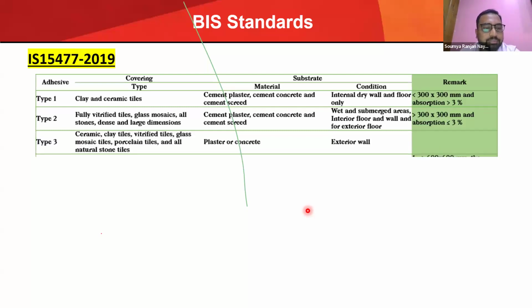Type 3 is the same kind of area we can use, but it allows for both external walls and internal walls, for all ceramic, clay, vitrified, glass mosaic, porcelain tiles, and all natural stones. As for size, it says that for greater than 300 mm you can use this, but it should be less than 600 mm for type 3.